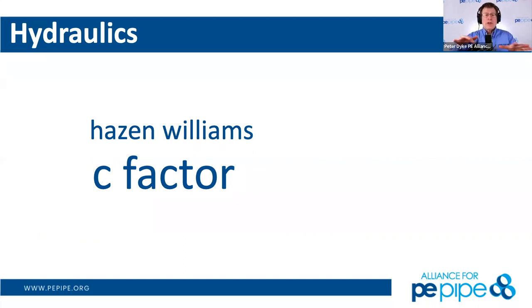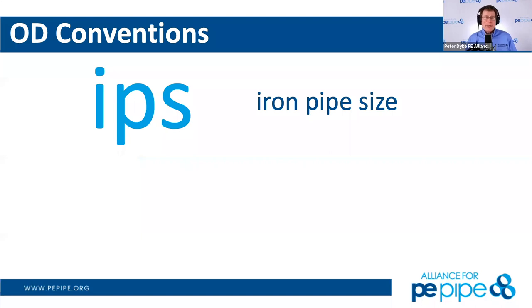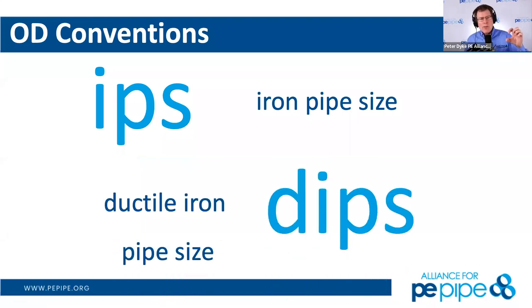The C factor, just like with PVC, is 150 for the life of the pipe. PVC doesn't support bacterial growth, neither does polyethylene, unlike the metal pipes. Next slide, please. So 150 is the C factor for the life of the pipe with polyethylene. We make IPS sizes, we make DIPS sizes. DIPS are marginally larger than IPS. The reason we make DIPS is so that we can match up with ductile iron pipe size. And we are pushing DIPS for municipal water throughout the United States. The reason you may find IPS more available sometimes is because IPS is used in all those other markets that I mentioned. Next slide, please.